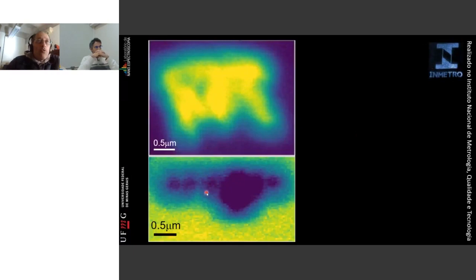So these are two Raman images. When I say Raman images, it means we are plotting the intensity of a given Raman peak. In this case, they are Raman peaks from defects in graphene that I already explained to you a lot. So there is a sheet of graphene here. There is another sheet of graphene here. And with a focused ion beam, we came and we made a picture here. And we came and we made another picture here.